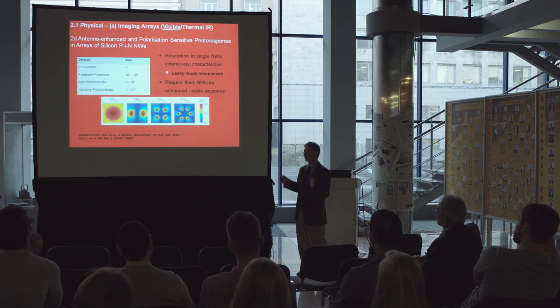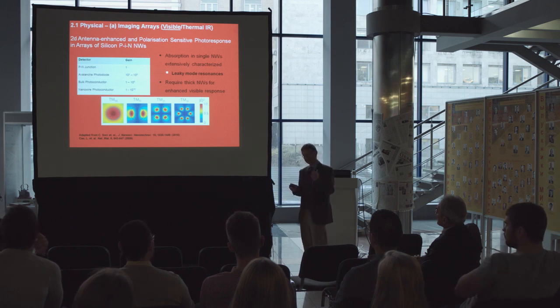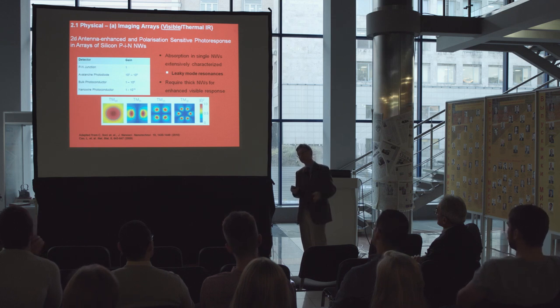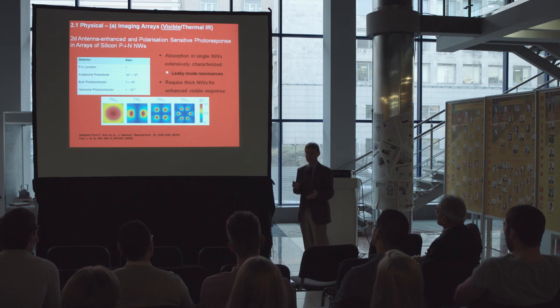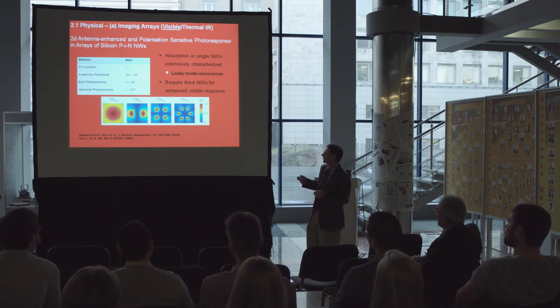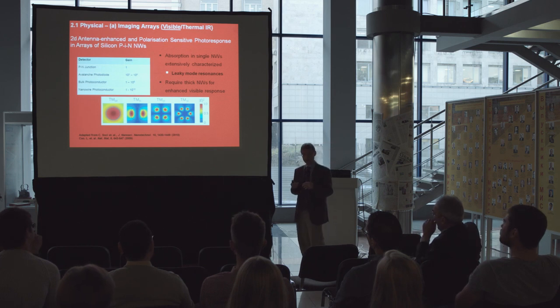Actually, let's say for a photoconductor for a minute here. Why? Because they will selectively trap one carrier, so the other carrier can keep cycling around your detector. So the gain, which is essentially a measure of how many times a carrier moves around, and therefore how big your signal is going to be, will be very large. If I look at a nanowire photoconductor, they can reach as much as 10 to the 10. So you have an inherently sensitive object, even though it's very small.